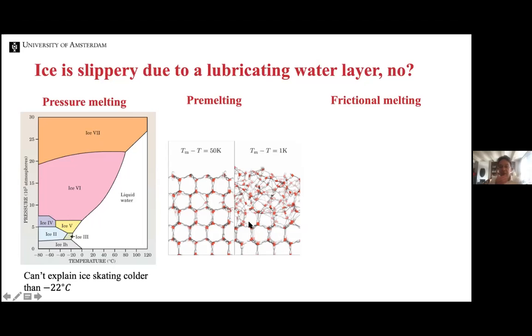The other idea that is widespread is that some solids melt at their surface before they do so in the bulk. And so if ice does the same thing, you could have a water-like layer at the surface of ice that could lubricate your skate if you're close enough to the melting temperature. That's called pre-melting. But again, this layer is, if present at all, not very thick, and only present very close to the melting point. And so this explanation is not really a very convincing explanation for why one can skate on ice.